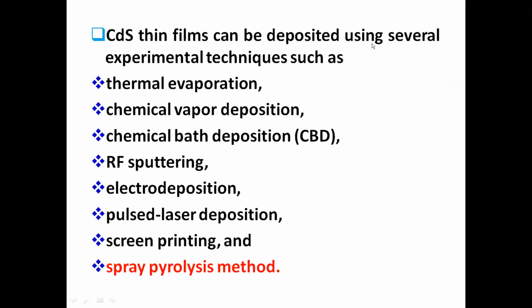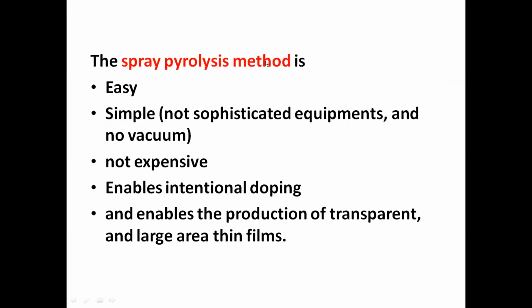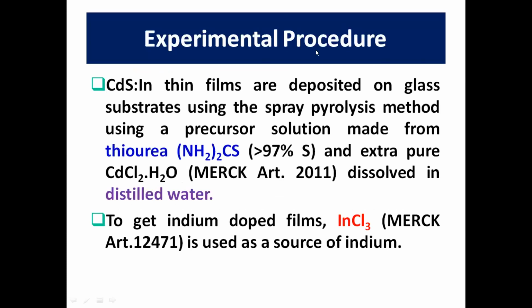Cadmium sulfide thin films can be produced by several methods: thermal evaporation, chemical vapor deposition, chemical bath deposition, RF sputtering, electrodeposition, pulse laser deposition, screen printing, and spray pyrolysis, which is used in this work. It is used because it is an easy and simple method, where no vacuum is used, no sophisticated equipment, and it is not expensive, and it enables intentional doping and the production of transparent and large area thin films. Now the experimental procedure.